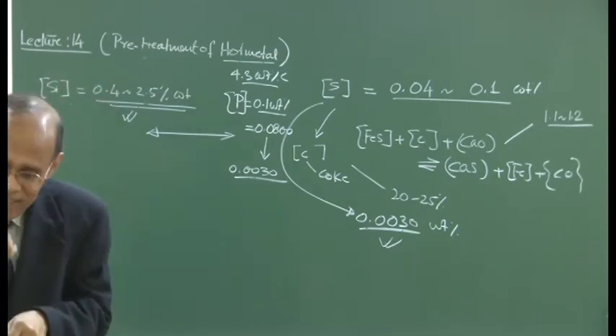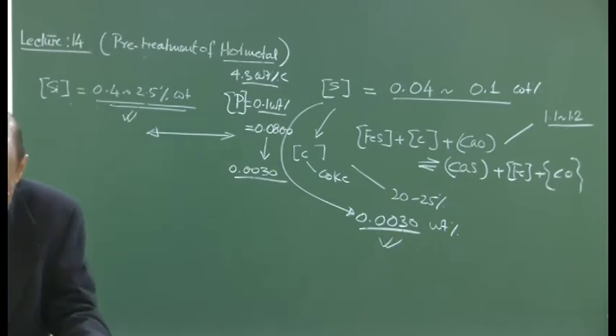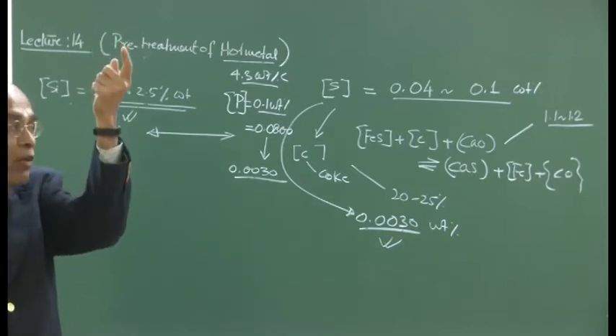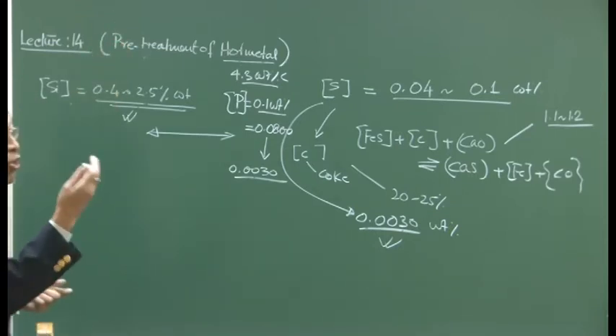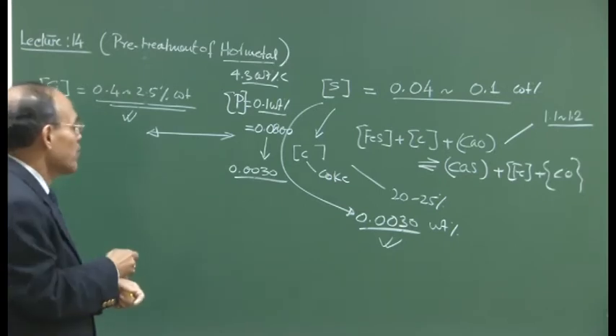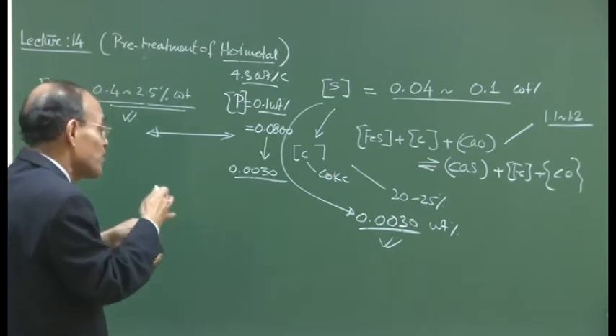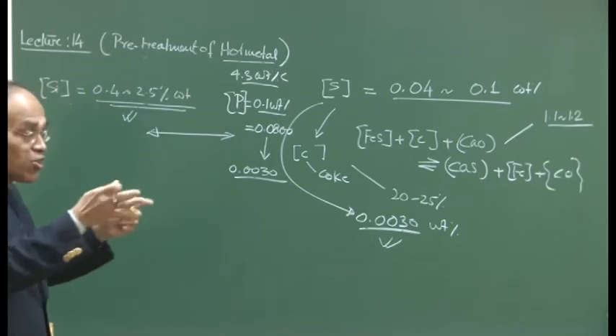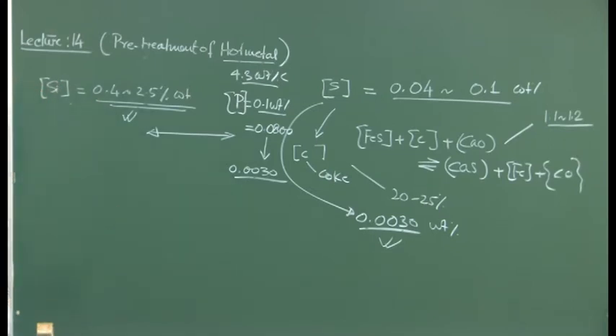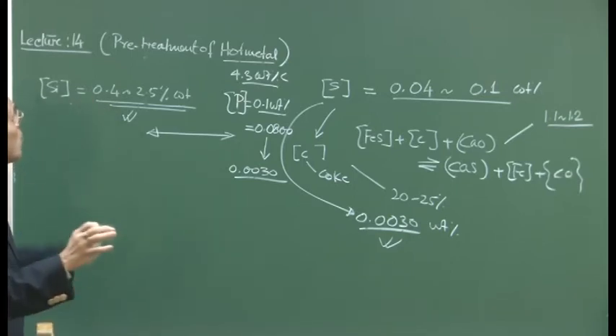It is facilitated at a little bit lower temperature, but if you have a lot of silicon, a lot of heat is being evolved, and as a result phosphorus reversion can take place because of that kind of high temperature, or phosphorus elimination may not take place unless you have cooled down the metal during refining by the addition of some solid coolants or so, which we will again discuss in greater detail later on. So, I think I have given you enough background to make the point why we should go for